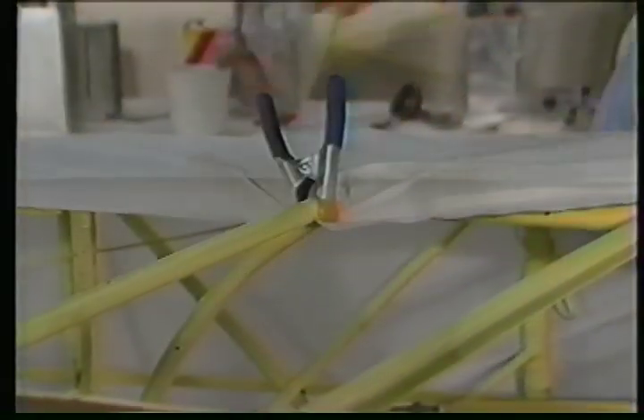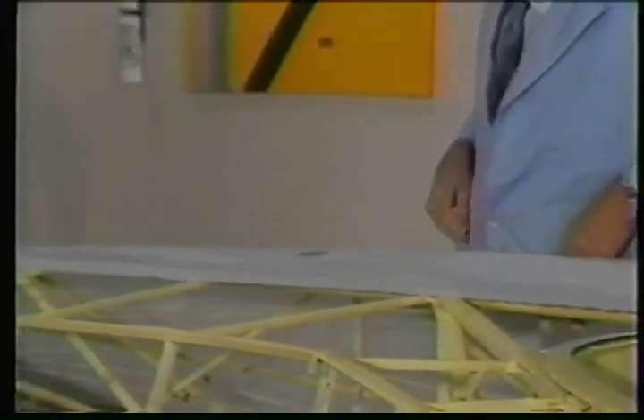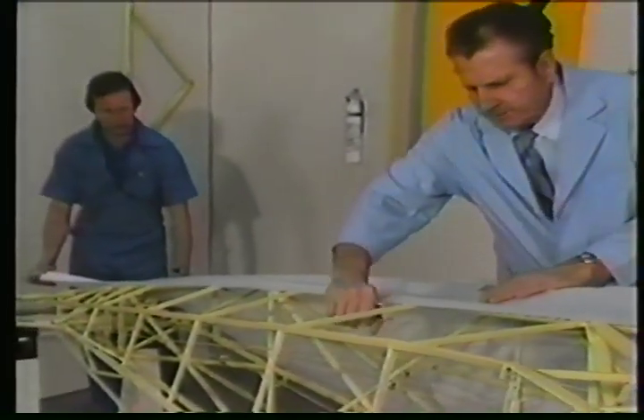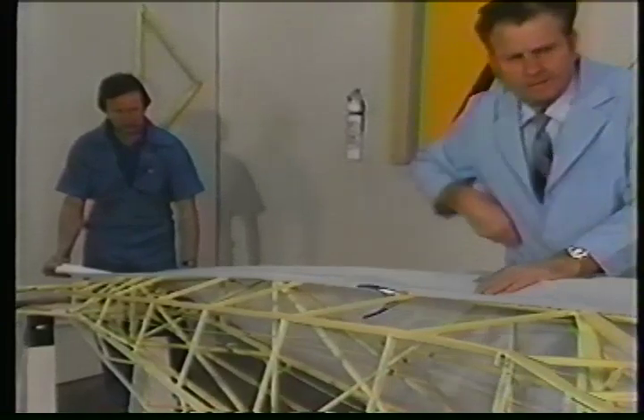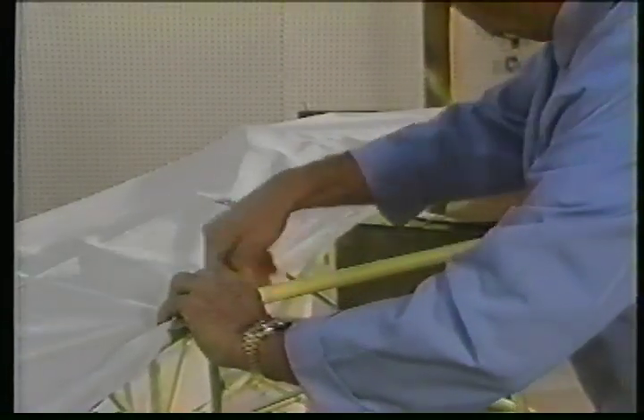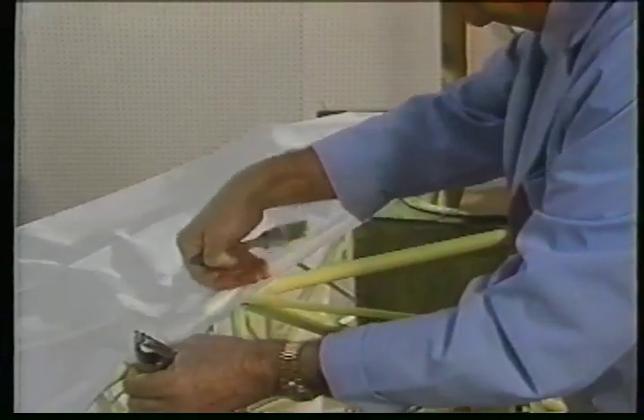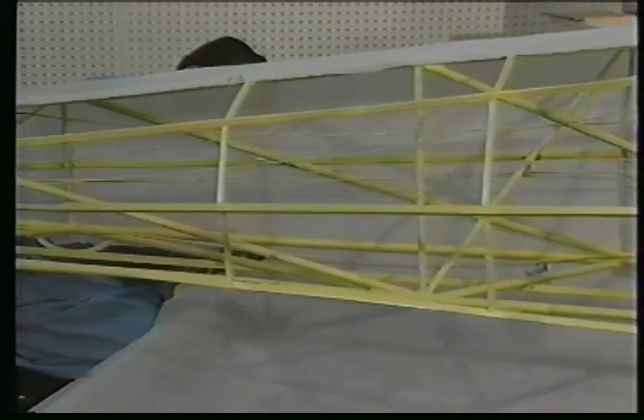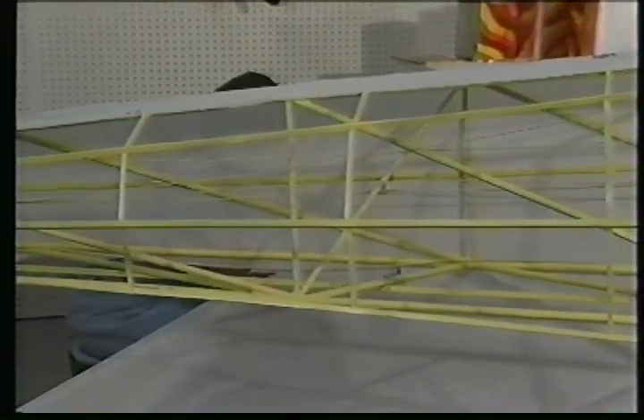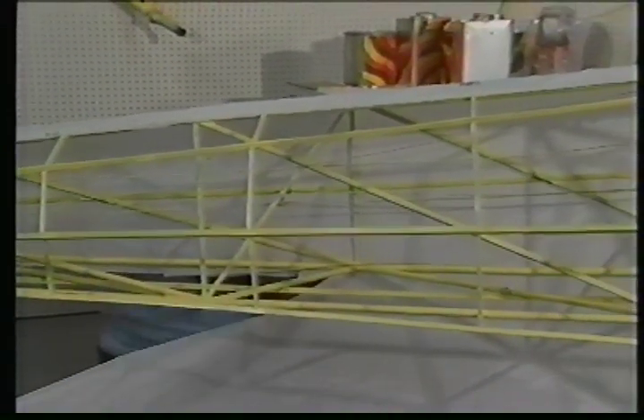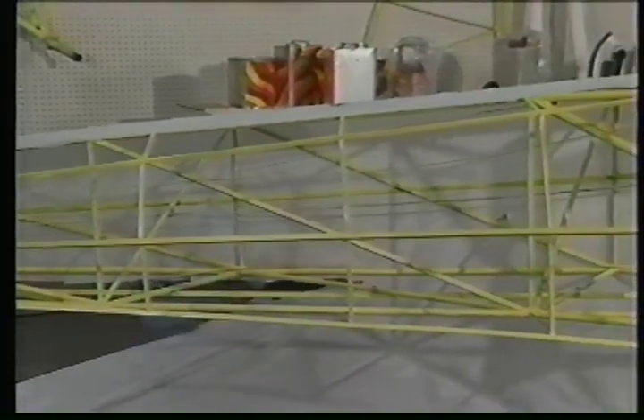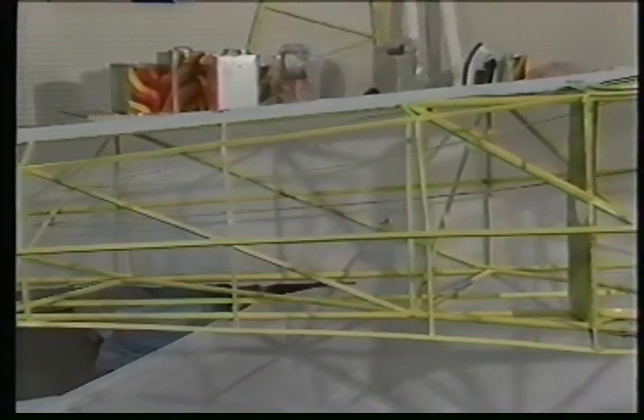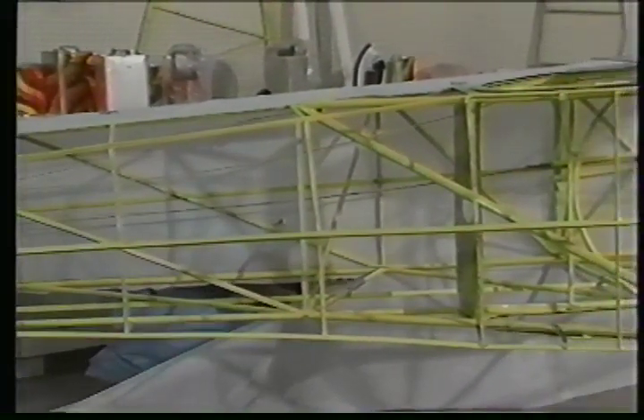The first section will be the left side with the fabric cemented to the upper longeron and extending around the bottom of the fuselage to the right lower longeron. The fabric is held in place with spring clamps. Then, starting at the forward end, attach the fabric with Polytack cement, the same as demonstrated on the wing. When the full length of the longeron is completed, pull the fabric snug, rough trim 1 inch past the longeron, and cement to the right lower longeron starting at the forward end.